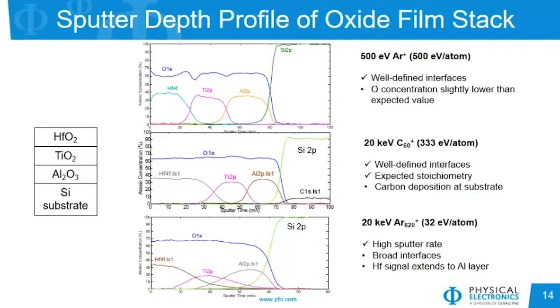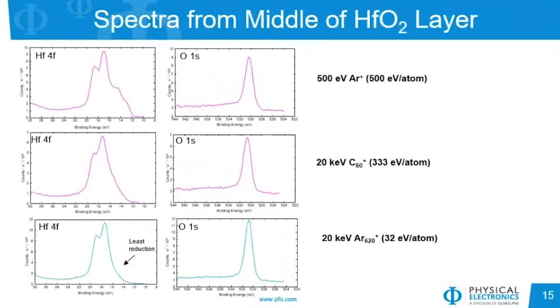So as you can see, there are some trade-offs for each of these types of sources related to the stoichiometry that we detect, or the broadening and interface quality. If we also look at the spectra itself from this analysis, we are looking at the hafnium 4f spectrum taken from basically the middle of the hafnium dioxide layer, in addition to the oxygen 1s spectrum.